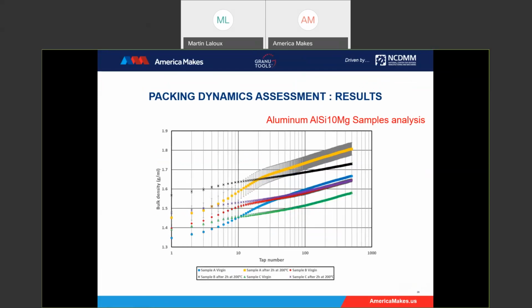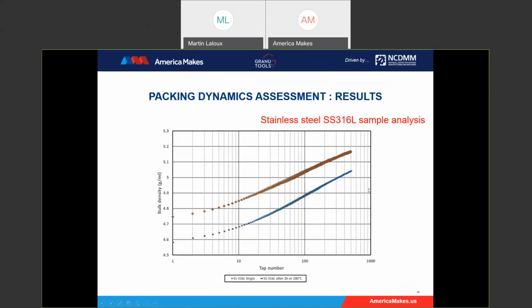Regarding the aluminum alloys, we observed that the sample A virgin, in blue, has the lowest bulk density compared to the sample C virgin, in green, and the sample B virgin, in red, which are close. But after 500 taps, we observe that sample A has the highest tap density compared to the 2 others. After the heat treatment, sample A has a higher tap density than B, than C. When we look at the stainless steel, we observe that the virgin one has a lower bulk and tap density than the heated one.